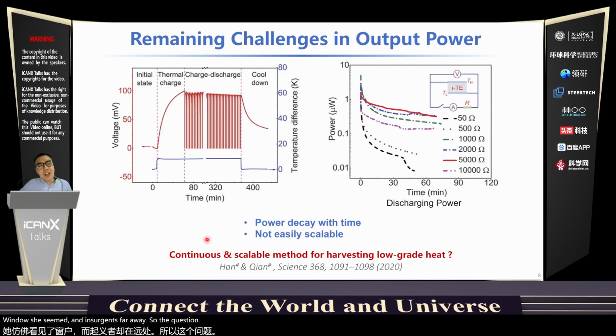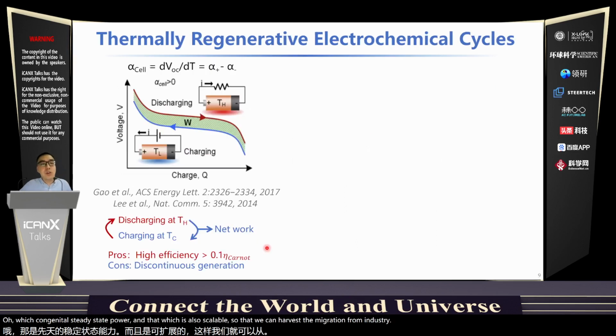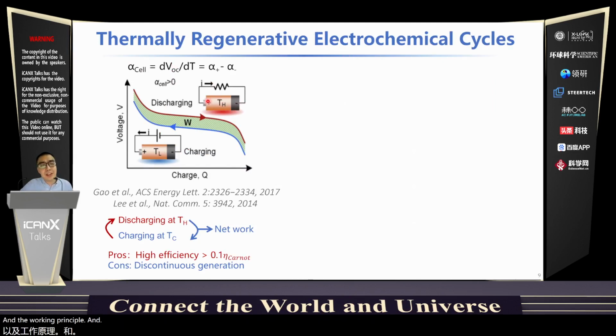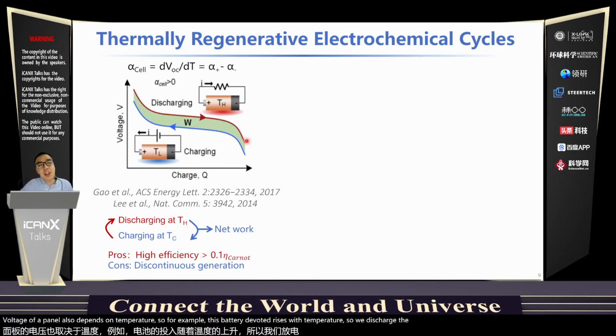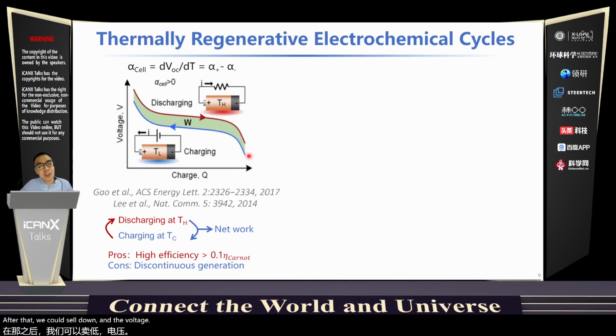So the question is, do we have a continuous method which can generate steady state power and which is also scalable so that we can harvest low-grade heat from industry? To do that, we actually look into a different mechanism, which is called a thermally regenerative electrochemical cycle. And the working principle is basically the voltage of a battery also depends on temperature. So for example, in this battery, the voltage rises with temperature. So we discharge the cell at higher temperature when the voltage is higher. After that, we cool the cell down and the voltage is lower, and then we do the charge. Through this cycling, we can harvest some amount of net work.